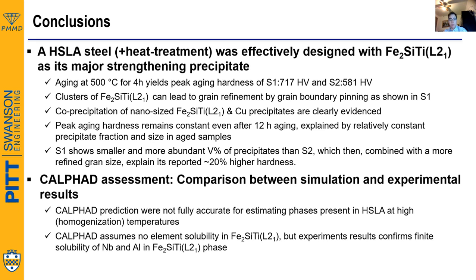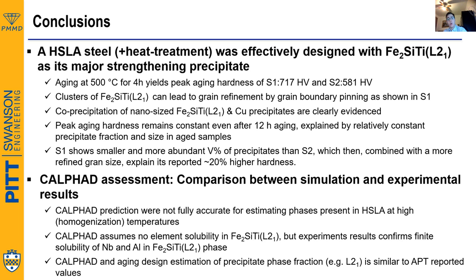but the APT results and the EDS results have shown that there exists a finite solubility of niobium and aluminum in the L21. So we propose an improvement on the CALPHAD database regarding the L21. But also, we should say that both CALPHAD and our aging model were accurate at predicting the volume fraction of L21 since the reported values of APT range between 5 and 8%.